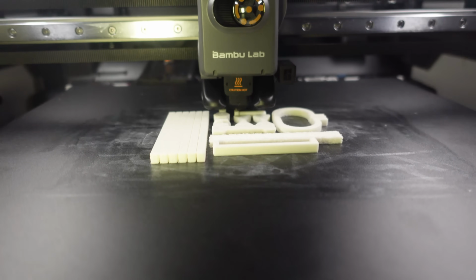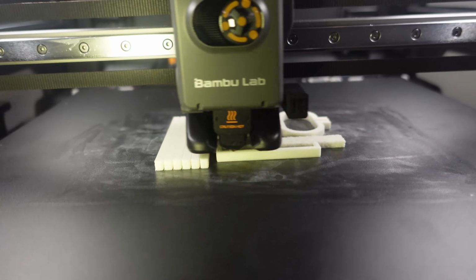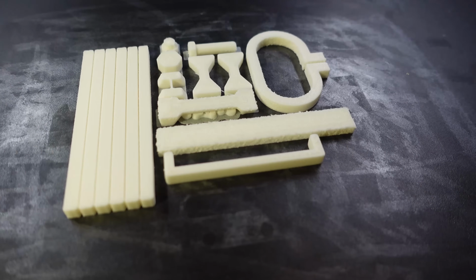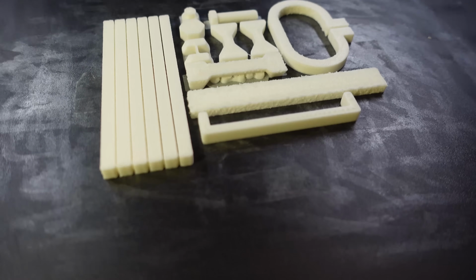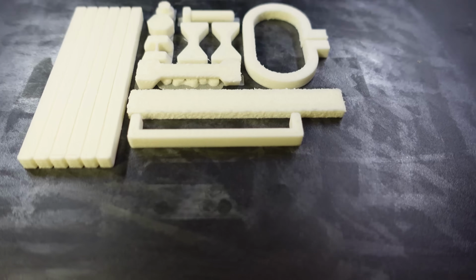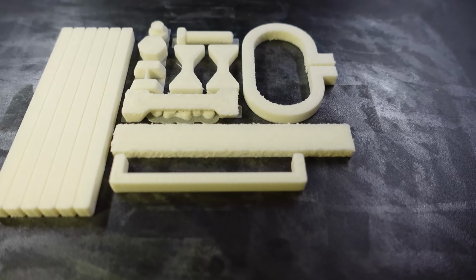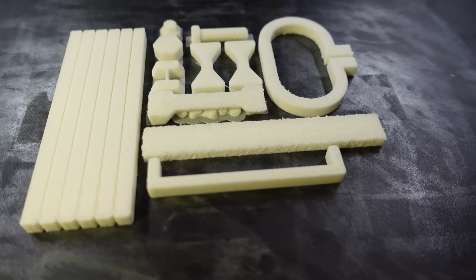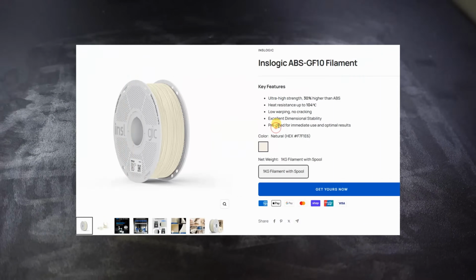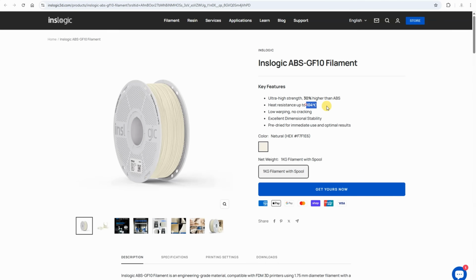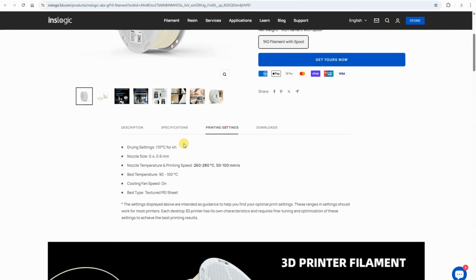Oh, but it looks like I have to stop the printing because this filament is not dried. I'm not sure if it is visible on the screen too, but pay attention to these side surfaces. Unfortunately, this needs drying, and then I will reprint these test objects. On the website they mention heat resistant up to 104 degrees Celsius, but drying is at 110°C for 4 hours. I'm sure this is an error.